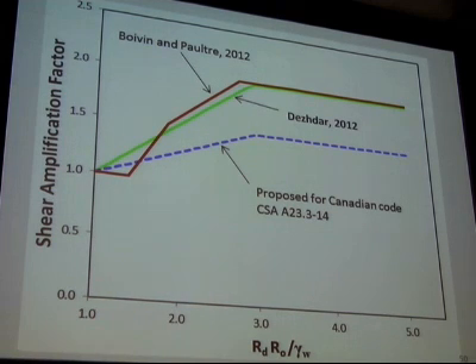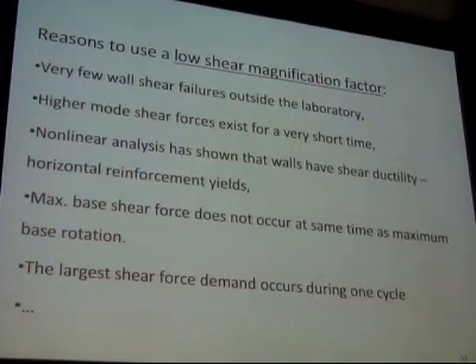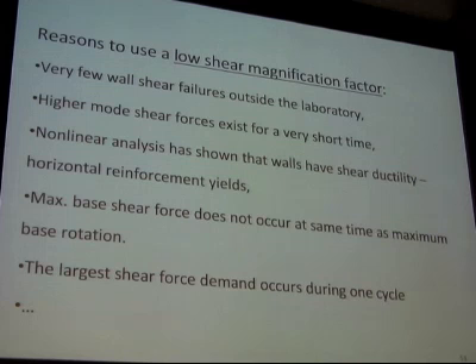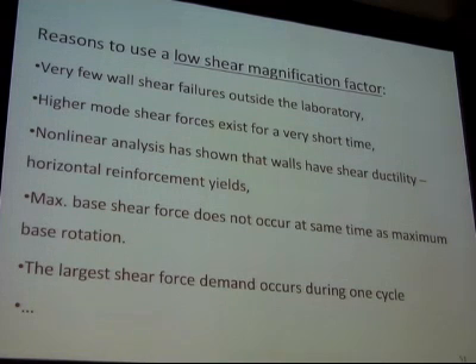And what we've done in Canada is we've gone to a reduced amplification factor. Instead of going up to 2, even though the data shows that we should go to 2, the code committee has agreed to go to 1.5 for a number of reasons. And here's a list of what are some of those reasons. First of all, we've seen very few shear wall failures in actual buildings. That the higher mode shear forces exist for a very short time. And by the time something starts to happen, the shear force turns around.